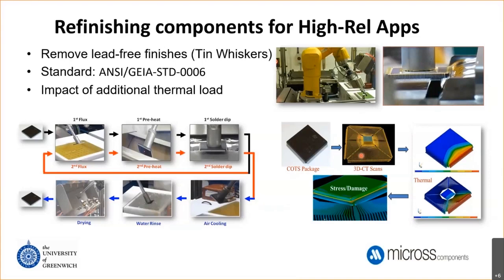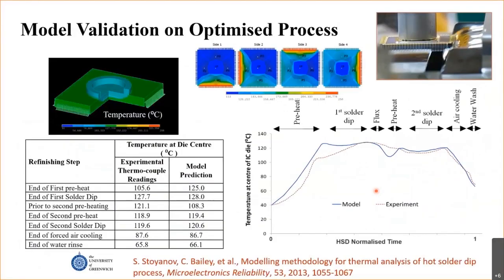In particular, could we get peeling stresses that may occur? There could be some moisture in the package still that could enhance that. So here we could see that to get the construction of the internal package, the use of CT tomography, and then that feeding right into the simulations to look at thermal behavior of the leads being dipped into the solder bath, and then also stress throughout the package and those interfacial stresses between the copper and the molding compound. So here you could see an animation of that component being dipped into the solder bath.